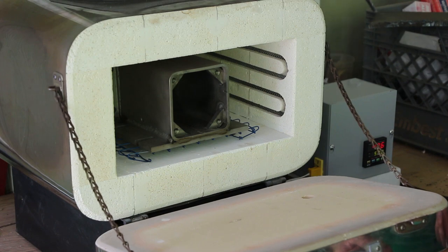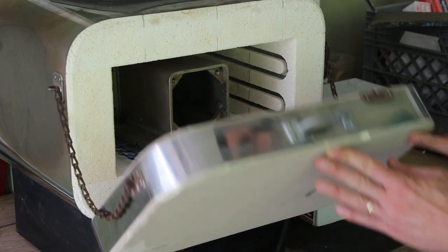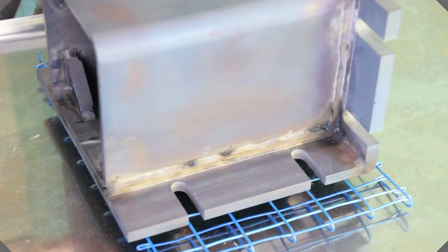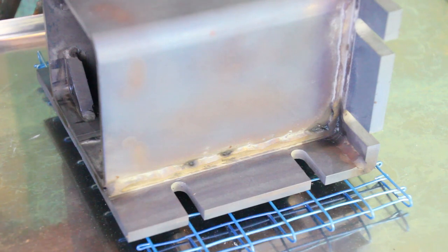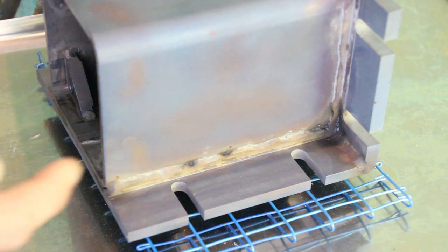Quite a lot of smoke in there, so I'd say it's not done yet. We'll keep cooking. I had to cook this thing for three hours before the smoke stopped coming out, and obviously it's heavily oxidized, so I'll have to sandblast it again to clean it back down to bare metal.